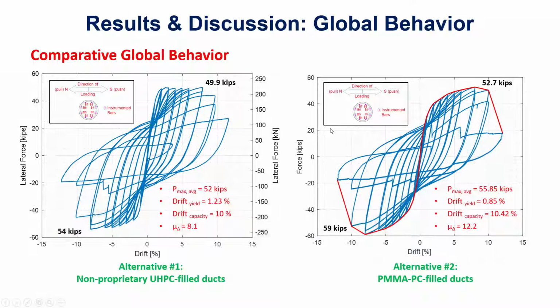We compared, as I said, with several previous columns from the old projects, and this is just a sample comparison with one of the similar identical columns that used non-proprietary UHPC. As you see here, alternative 1 versus the polymer concrete in alternative 2, and they were very comparable, same dimensions, same column design, and the failure load in the polymer concrete was even slightly higher.